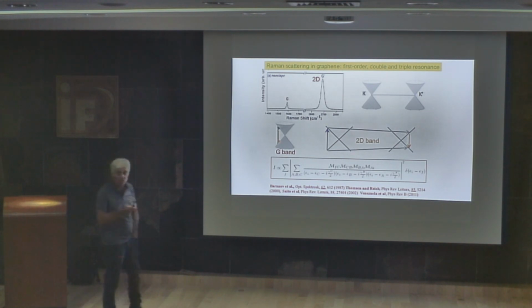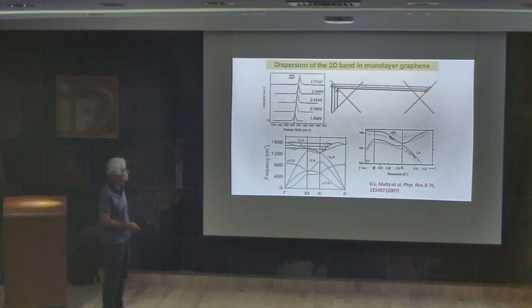And this is the signature of single-layer graphene: the fact that the 2D peak is stronger than the G peak, even though this is a normal process, and this is a higher order process. And this peak is very useful to get information about graphene and other 2D materials.